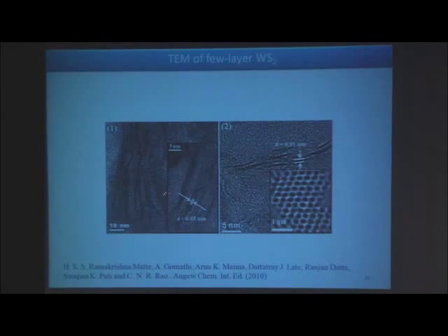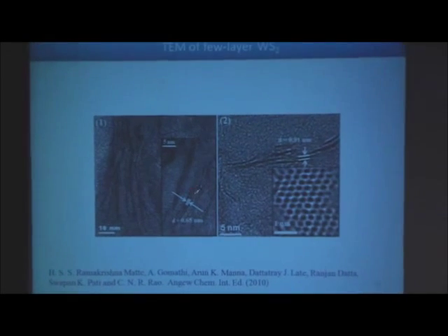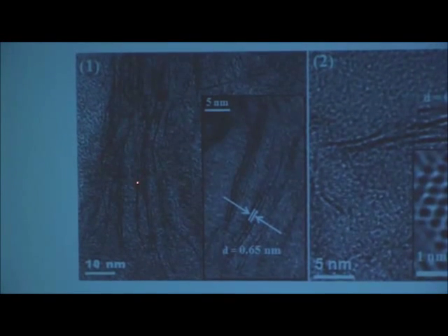See, this is the electron microscopy. You see, there are only 2 layers, 3 layers, 2 layers, 2 layers, 3 layers, 2 layers, 3 layers. And this is the high resolution tungsten sulfide. So inorganic analogs of graphene have been made in our lab successfully.